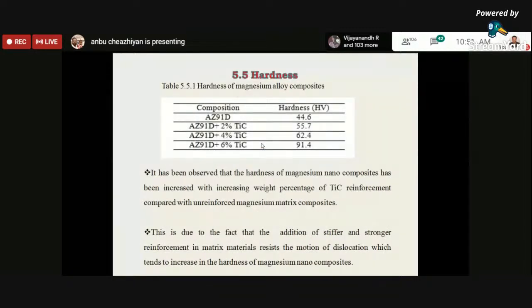So these are the hardness values of the magnesium nanocomposites. When compared, the Vickers microhardness has improved. It has been observed that the hardness of the magnesium nanocomposite has increased with the increase in the percentage of titanium carbide reinforcement when compared to the magnesium alloys. This is due to the addition of stiffer and stronger reinforcement, high density of dislocations, and reduction in grain size.